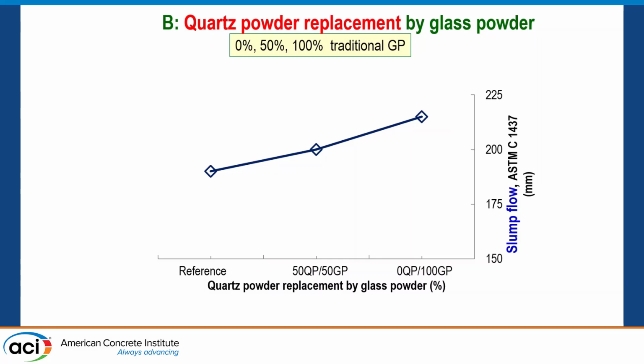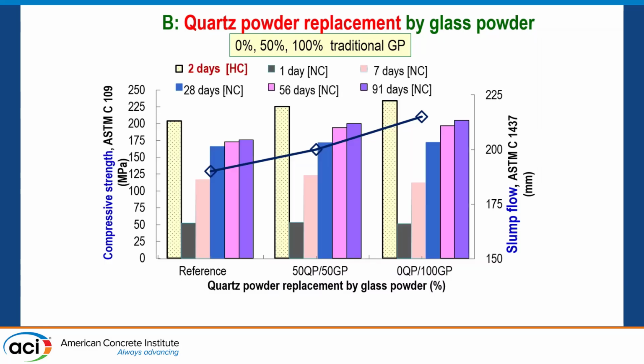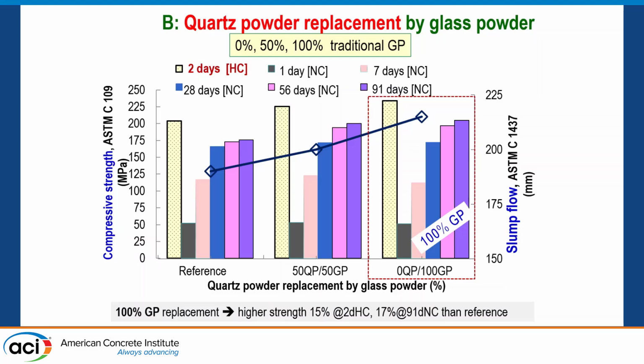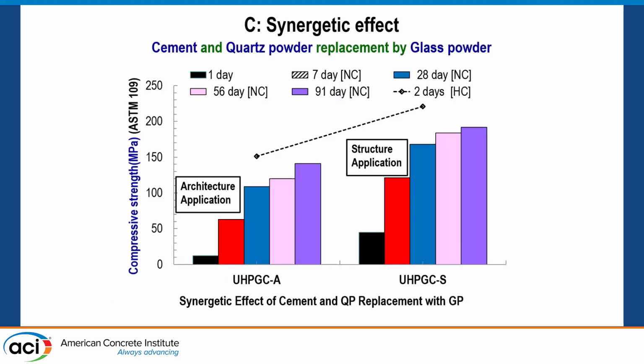Now, if you replace the quartz powder by the glass powder, the same thing, you see the slump going up, and also you have the compressive strength, which is good at a given level. So you can, in this case, go to 100% complete replacement of the particles of the sand. Now, if you mix them, then you can classify your materials like 2. So if you want to go for more architectural application, then you have a very good flow and the material can fill up very well the molds. If you want to go to more structural, then you have to pay something about the slump, but you can get a high performance.